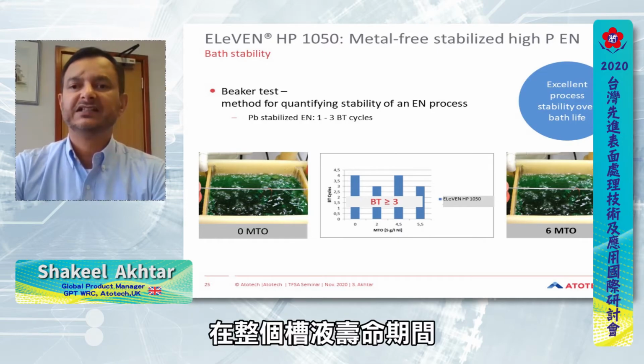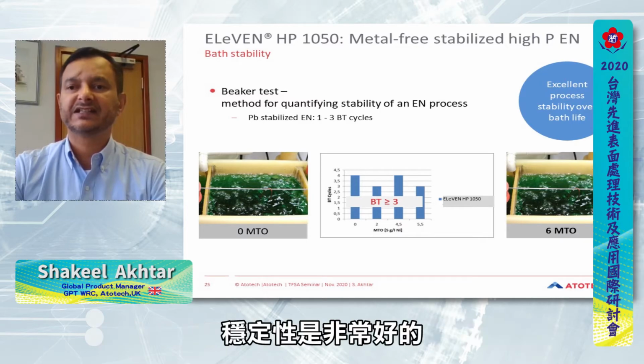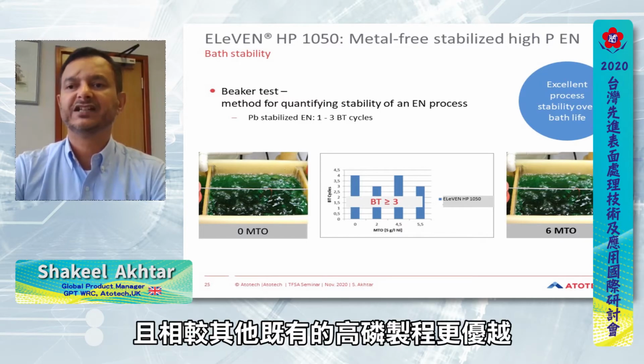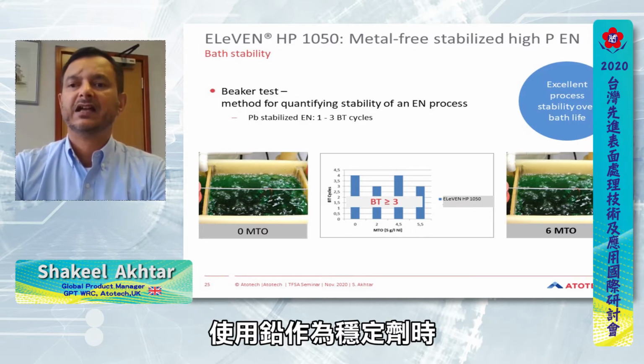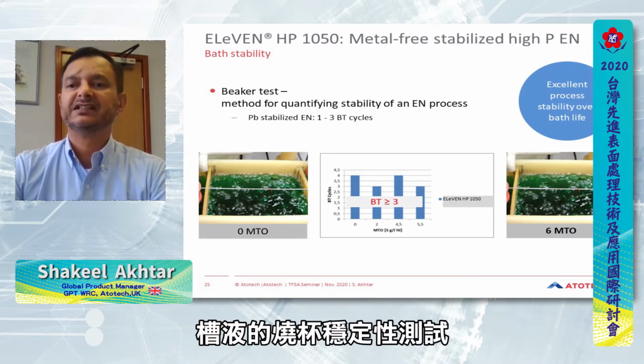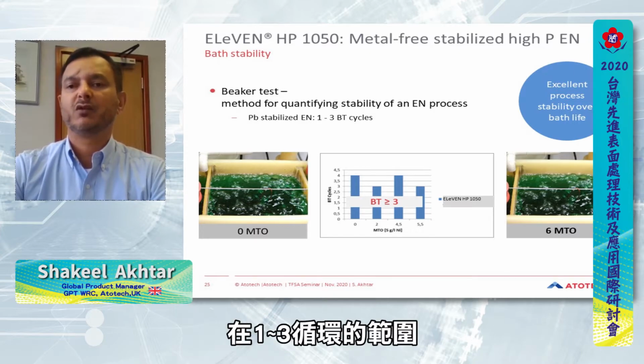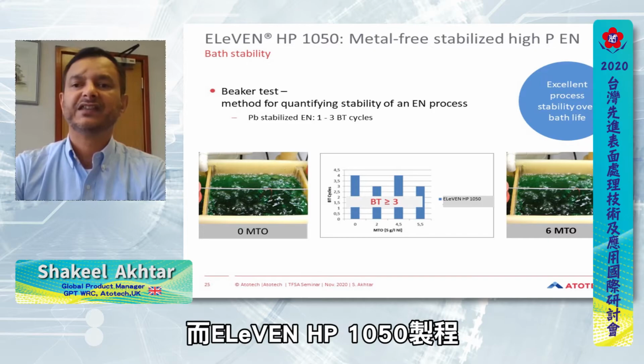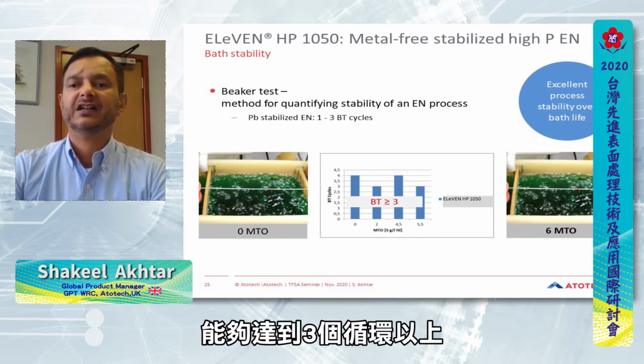The bath stability of the HP 1050 is extremely good and is superior to the existing processes over the whole bath life. With lead stabilizers, the bath beaker stability test is in the range of 1 to 3 cycles. With HP 1050, we are able to achieve more than 3 cycles.